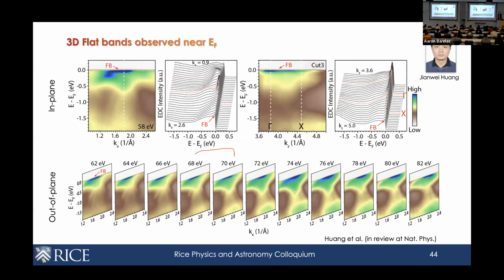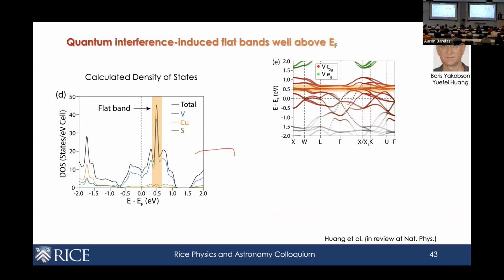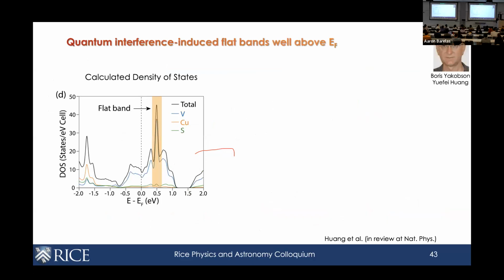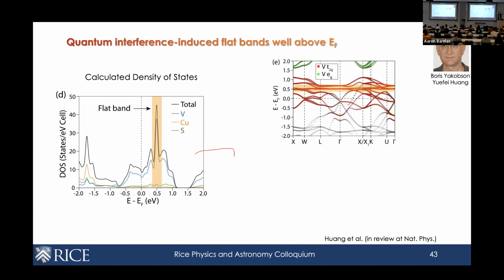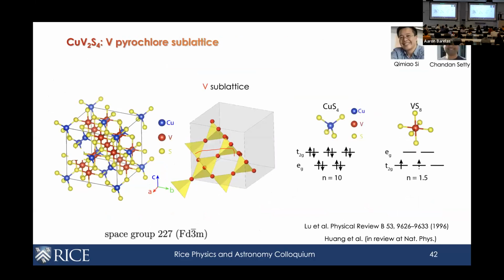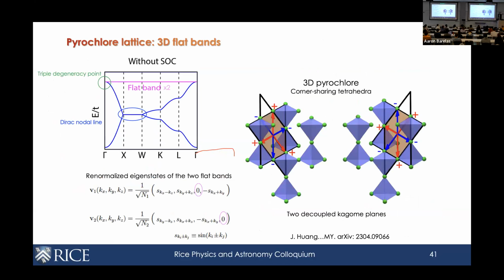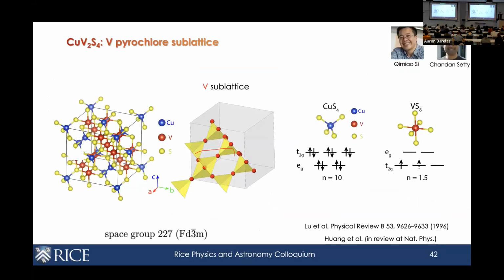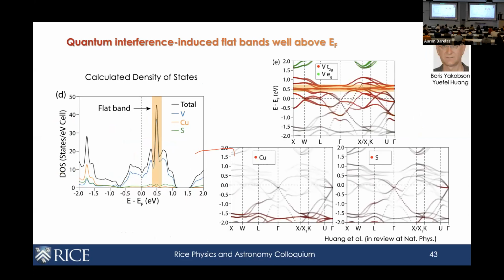Oh, this is a very good question. What I showed you is the tight binding calculation. Ben asked, is there a flat band in every kagome system? The answer is that in this simplified picture, if you assume there's no hybridization between the kagome sublattice and the rest of it, that is likely true. But in this material, I sort of ignore the other stuff here. If you have a strong hybridization between the vanadium sublattice and copper and sulfur, then that will destroy that flat band. So for this system, if you look at this DFT calculation, this one is relatively flat because there's very little hybridization. Maybe some sulfur comes in, but there's lower hybridization here than in some other compounds, some of the Laves phases, for example, where there's stronger hybridization.